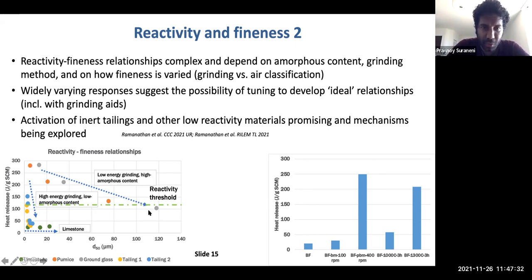What's interesting, of course, is that for very coarse materials, we actually register them as inert because they fall below the reactivity threshold. They're not truly inert. It's just that they're so coarse that the reactivity is going to be very low unless you expose them for very long periods of time. On the other hand, we took very low amorphous content materials. In fact, these materials, when tested as is, would be inert, and we subjected them to high energy grinding. So this grinding was done using a disc mill. And here you see a completely different relationship. In a very small range of amorphous content, in a very small range of fineness, these materials go from inert to actually reactive. So we've activated these materials through this grinding process.